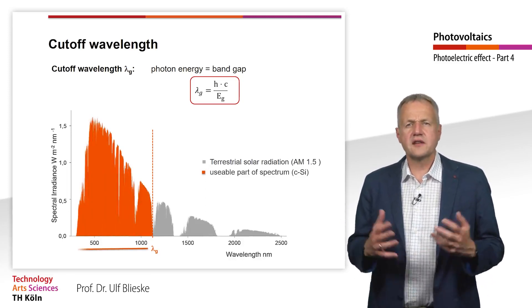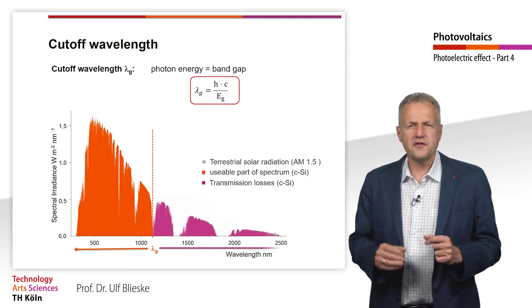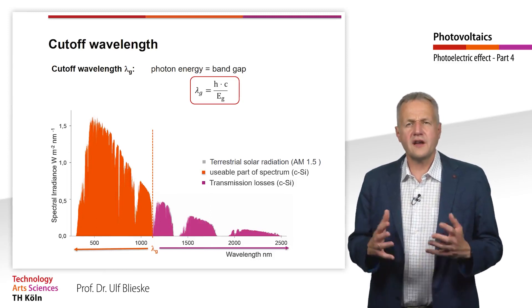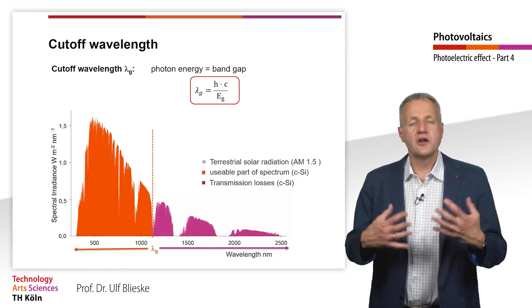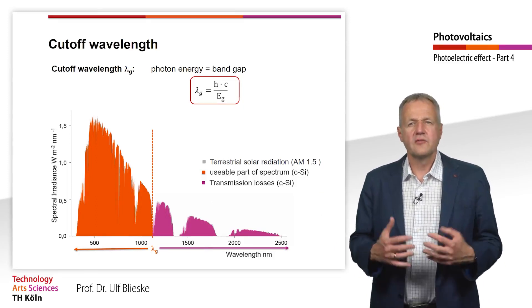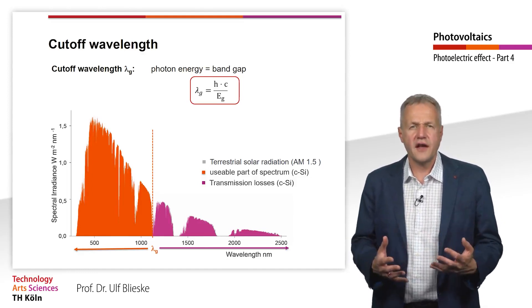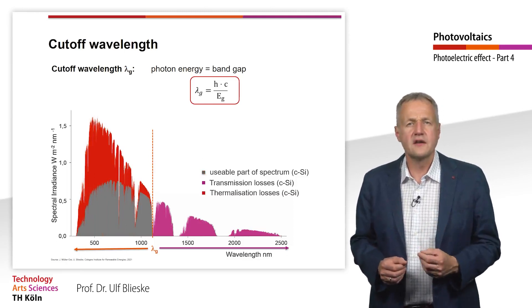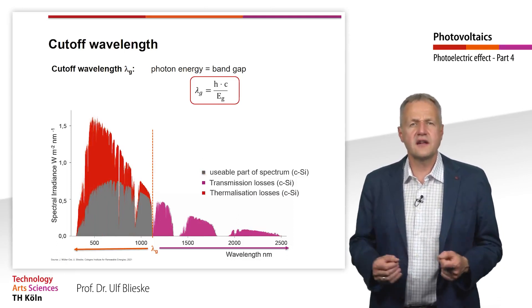The part of the solar spectrum that can be used for this material is drawn in orange — this is the portion of the spectrum with wavelengths less than the cut-off wavelength. In a solar cell made of crystalline silicon, photons with a wavelength larger than the cut-off wavelength contribute to transmission losses, shown to the right side of the cut-off wavelength in the diagram. In contrast, photons with a wavelength smaller than the cut-off wavelength contribute to thermalization losses, where the excess energy is released as heat to the crystal lattice.